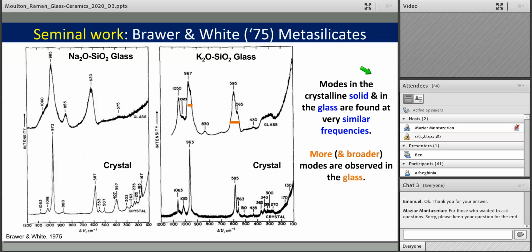These insights about silica were at the same time accompanied by insights about the other silicate compositions. This is a seminal paper by Brawer and White, and even by today's standards, this is an excellent paper. They compared glasses and crystals of the same composition. Here we show on the top sodium silicate glass, and on the bottom the crystal. Here a potassium metasilicate glass, and on the bottom the same crystal.